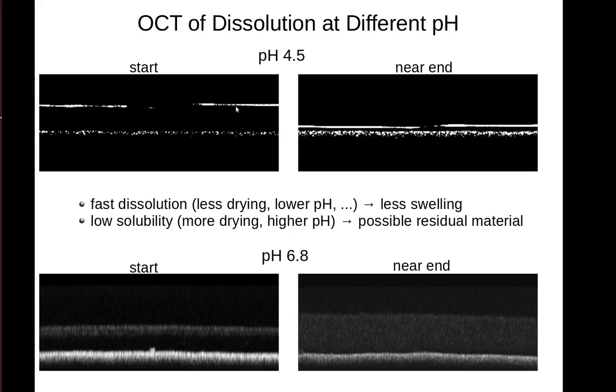Just from the static images we can see that for a pH of 4.5 it looks like the film just gets dissolved from top down, whereas at a pH of 6.8 it looks like there's quite a bit of swelling. It goes from almost probably a 50% increase in the thickness. The following will show a time-lapse video of these images.